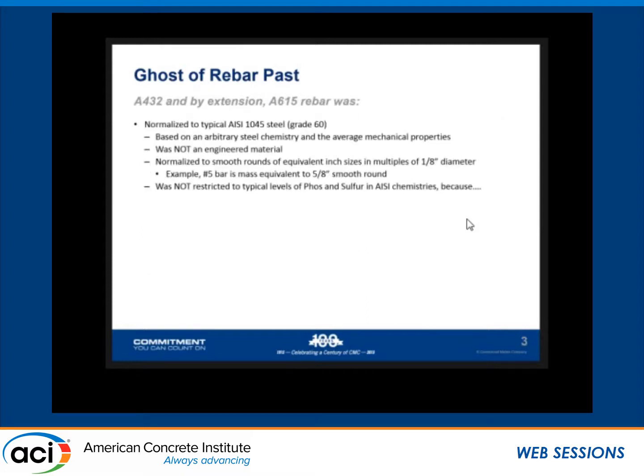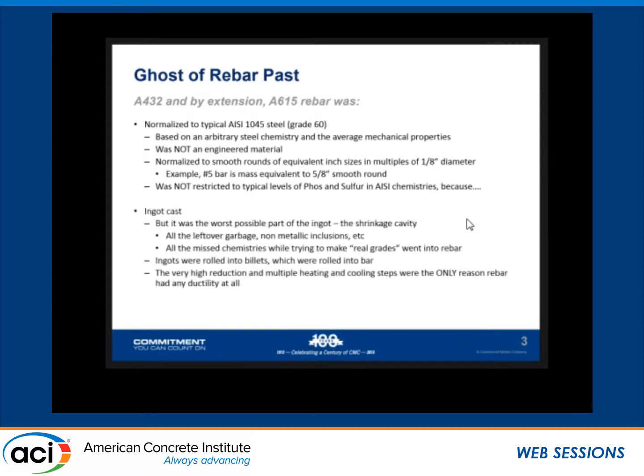Of a number 5 rebar, it's basically a 5/8 inch round, not restricted in just about anything. The only limit they put was on really, really high phosphorus, and the reason they didn't restrict more was because steel back then was mostly ingot cast. Now, that in and of itself doesn't matter, except that rebar was the worst part of the ingot. You took the part that had all the crud, for lack of a better way to put it, that just floats to the top. You get this tapered shrinkage cavity, and then you cut that off, and all the good stuff went into something else, and that leftover shrinkage cavity went into rebar.